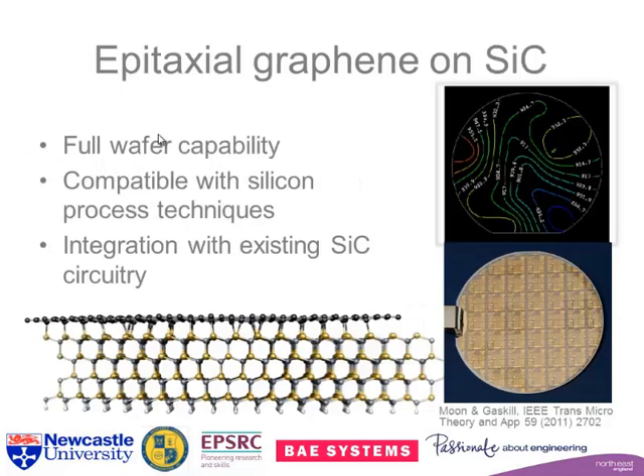So epitaxial graphene we get from thermal decomposition of silicon carbide. The big advantage of this is we have full wafer capability. The Scotch tape method generally produces much smaller fragments. So here's a Lehighton resistance map of a 4-inch silicon carbide wafer, and it's got something like a 2% resistance variation across 4 inches, and that's a fully processed one. That's a 3-inch wafer because it's last year's picture, and that is one atomic layer of graphene completely across a 3-inch wafer.